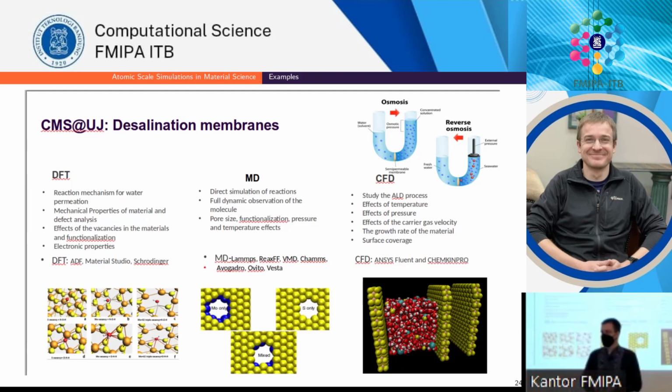So the setup, as you can see on the bottom right, would be, in this case, you have in yellow molybdenum disulfide sheets, where, for example, the middle one would have a little hole in the center, as you can see in the middle bottom. And then you would use the left sheet as a piston and just press the water through, right? You have to use a little bit of force. Okay. And then what we can look at is, depending on how big the pore size is, aka the hole in the molybdenum disulfide, how much of the ions in the system which we don't want to go through are retained on the left side, right? And we can see that in this kind of setup, this is about, say, 70 to 90% retention. So you have just 2 layers of that.